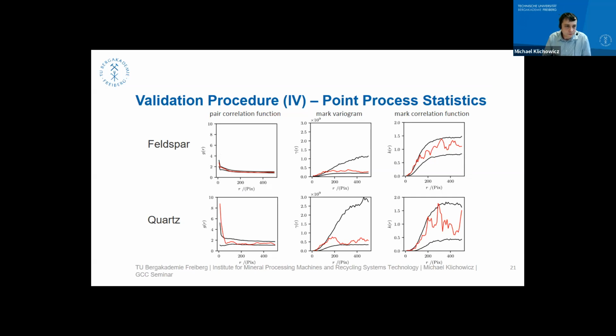And this pair correlation function is the average number of points in a distance r, and it represents the variability of the interpoint distances. And for random processes, so if you have a random Poisson process, that is always 1, and it is large for clusters. So what we see here, for larger distances, it converges to 1, so it should be a random point process. But for smaller radii, it is higher than 1, which indicates that we have some sort of clusters in our microstructures at short distances.